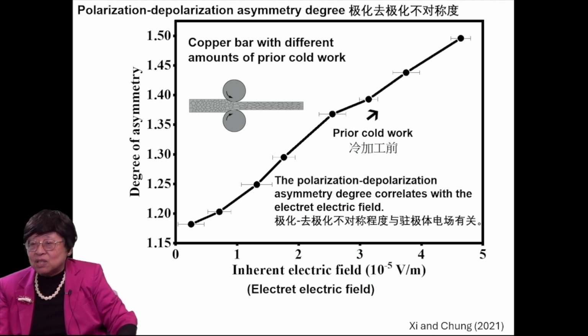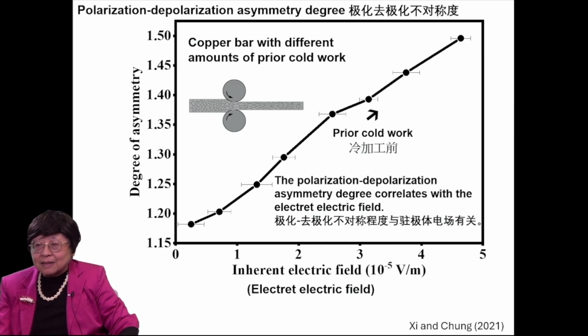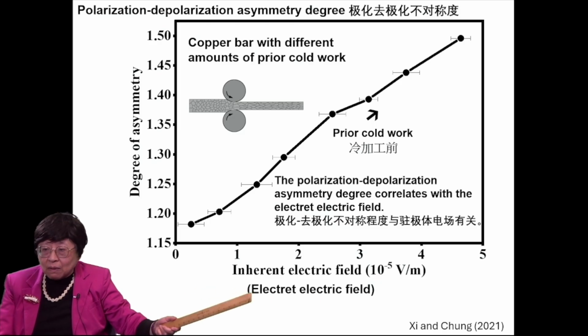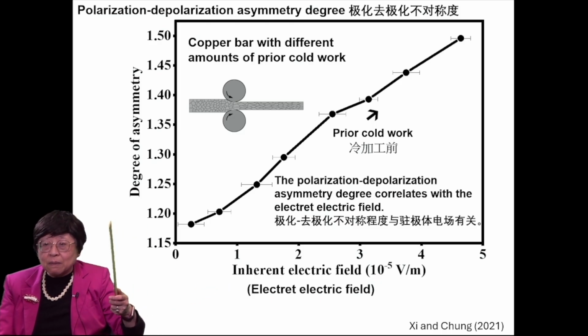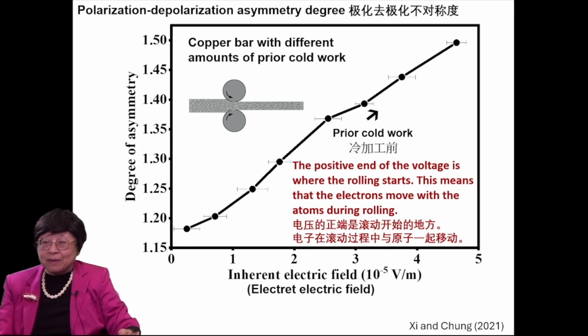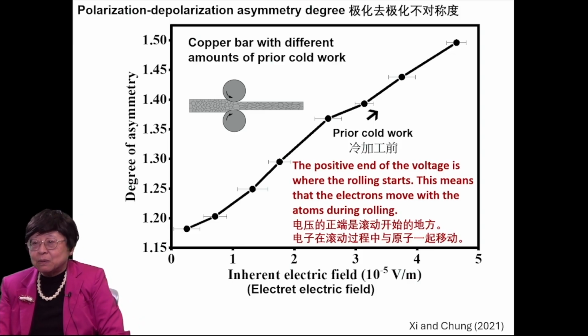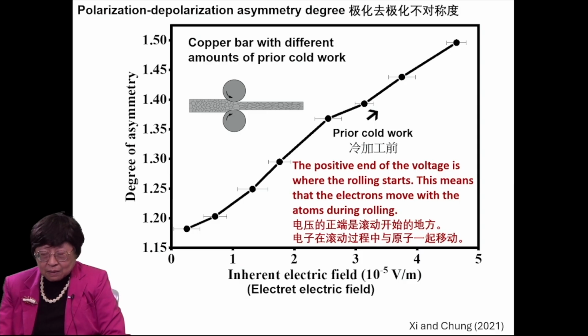So this again points to the importance of the microstructure refinement in promoting the polarization, and cold work would give you more microstructural refinement. That's more electric field and also more polarization, depolarization, asymmetry. Even more important is the fact that the positive end of the voltage in the electret is where the rolling starts. This means that the electrons move with the atoms during rolling. And this is in line with the occurrence of electron-atom interaction.